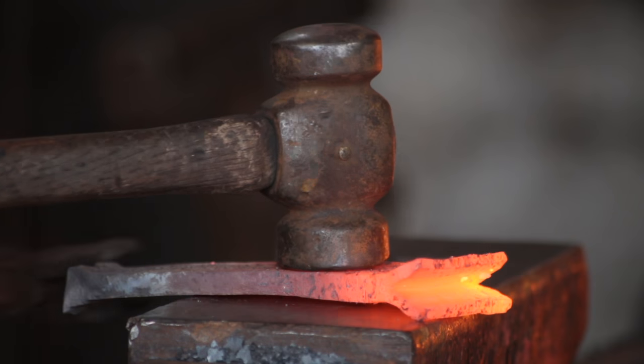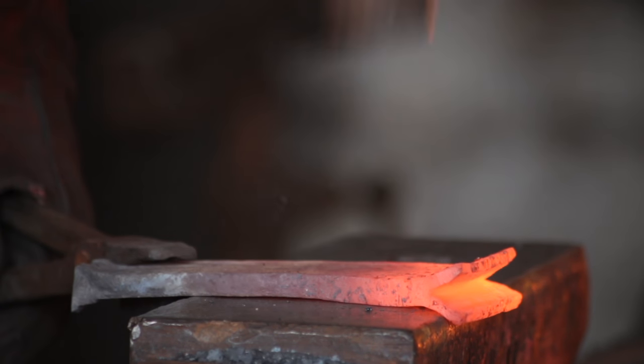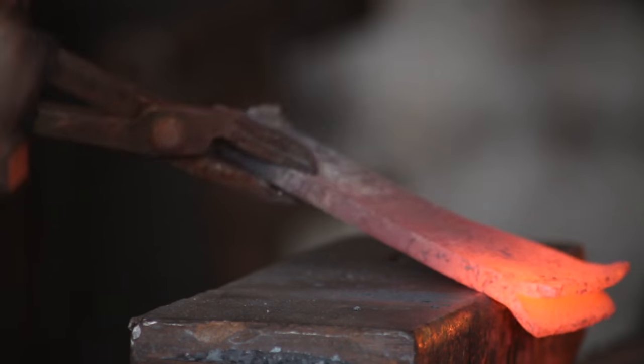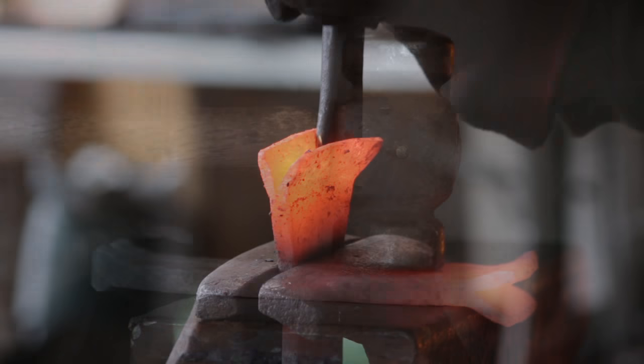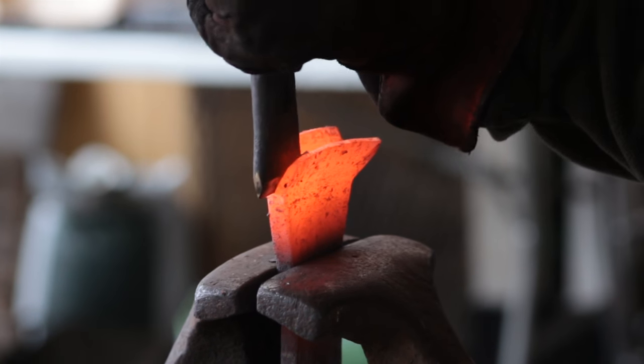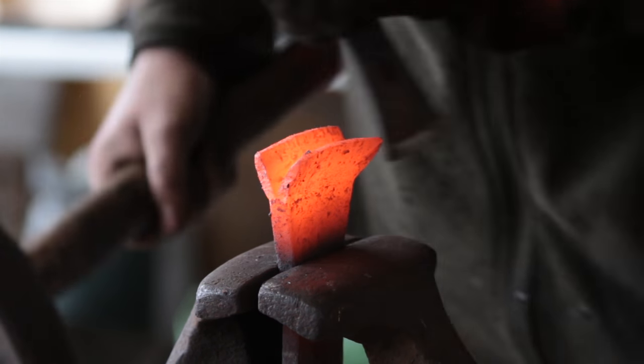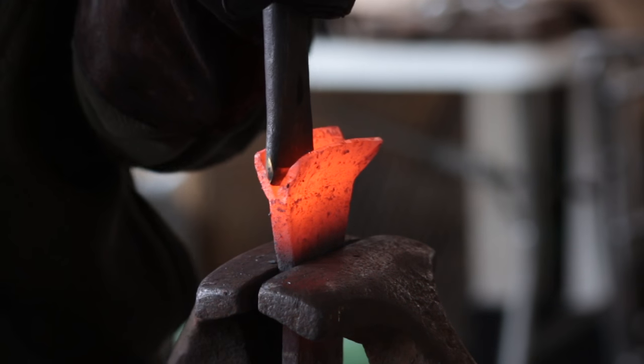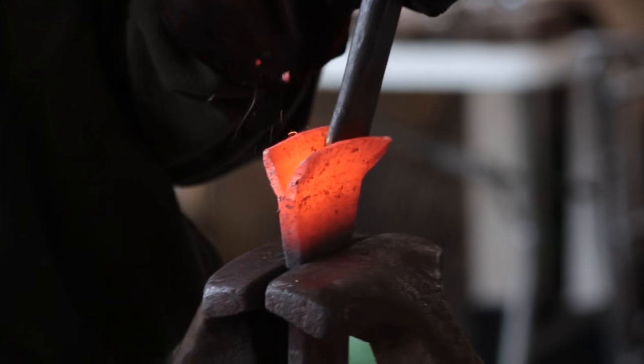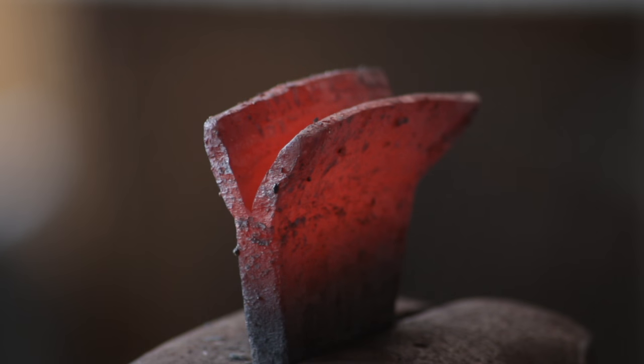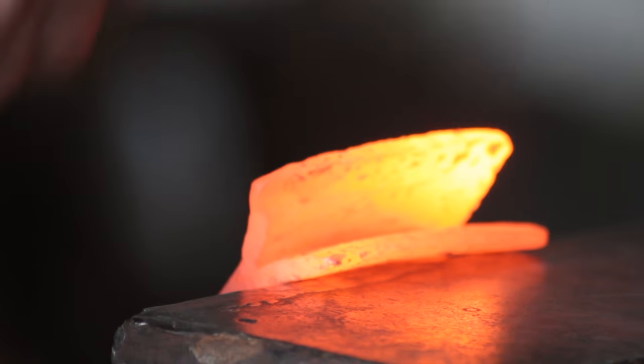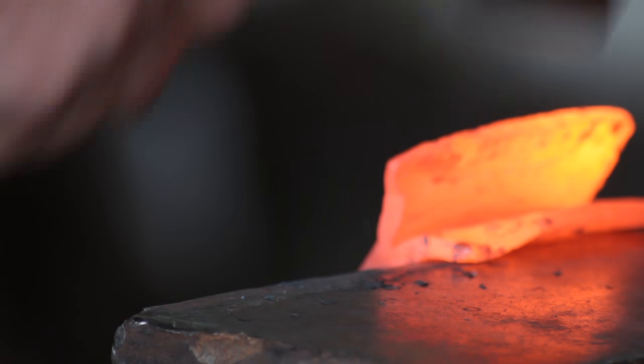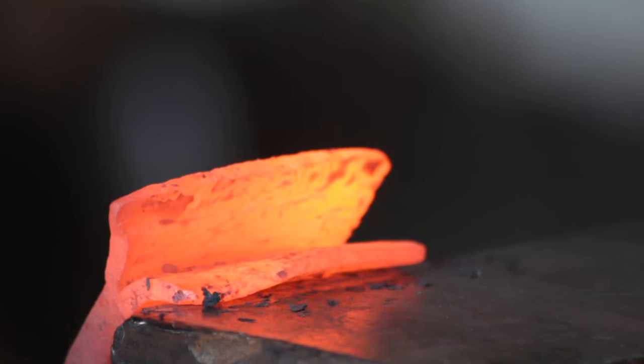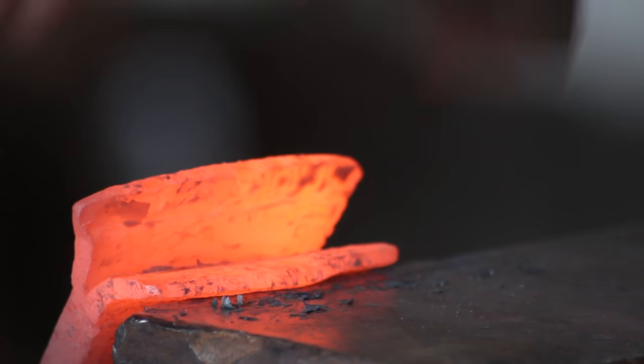Just to save it from overheating or losing its temper, etc. Give it a straighten between heats. And just keep going. And I went to a depth of around 20 mil. So the next stage is to thin out these lips a bit. And that is basically scarfing them to stop them from forming a shear plane.